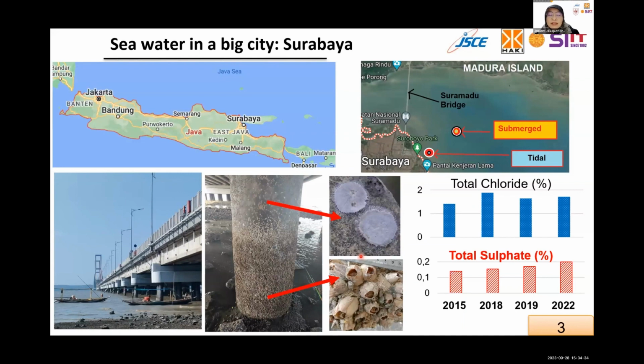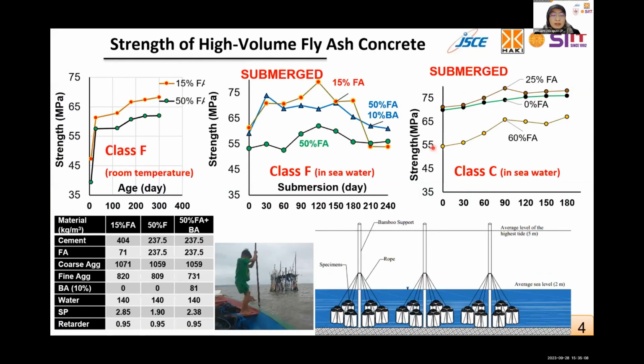In the study, we have made 2,000 specimens that are immersed, 1,000 in the submerged area and another 1,000 in the tidal area, as shown in the picture here. We observe the strength, the density, the mineral change, and everything for around 8 months. This is actually still ongoing, but I will share the current research. With high volume fly ash, where the cement is replaced by more than 40% fly ash, we hope the concrete is more durable and resistant to sulfate and chloride attack.